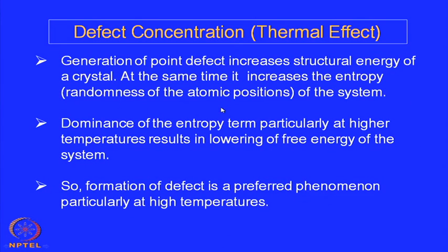Okay. Finally, I think there are only a couple of slides. Defect concentration, thermal effect. What we have discussed so far is that the defect concentration changes with the partial pressure, because it equilibrates with the environment. Depending on its preparation condition and the environmental condition, the partial pressure, the defect concentration will change, and accordingly its conductivity, its mobility, its diffusion coefficient, all of them will change, whatever is related to the defect concentration, whether it is ionic defects or electronic defects, right.